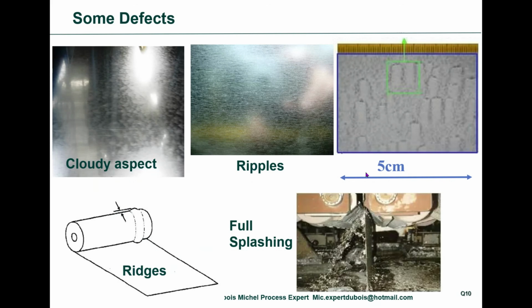Of course, I have a collection of some defects, but you have to keep in mind that the defect you see on the final galvanized sheet is a combination of wiping and solidification. Sometimes it's not easy to be sure which one is responsible for what. So a quite well-known defect is a cloudy aspect. Those types of clouds on the surface are typical of air wiping. That's why nitrogen wiping has been used to solve that problem.